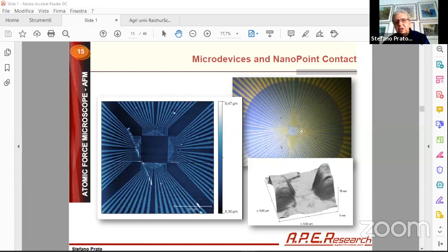In this case, we switch to the atomic force microscope, okay? So this central area here is what you see here. So this is an optical image, and this is the zoom done at the center, done with the AFM, okay? In this case, it is a very large image. This is 100 by 100 micron. Okay, it's very large. It's one of the largest that you can get with our instrument, for example. So what is here is again some contact. As you see here in the center, you have some gaps. This is the 3D AFM image acquired in this area. So this size is 100 by 100 micron, and this is 200 by 200 nanometer. So this gap here is around 200 nanometer, okay?